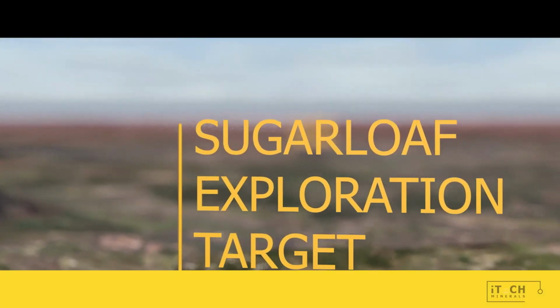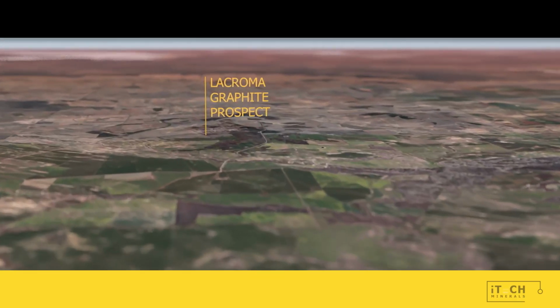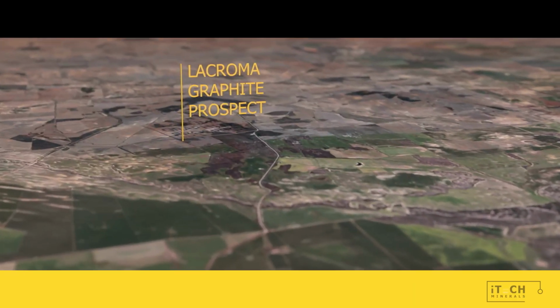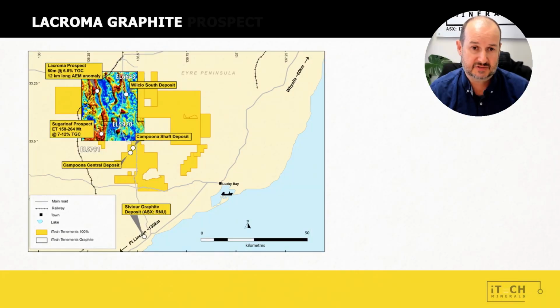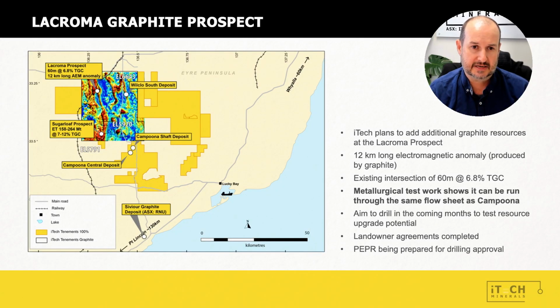So the next target we have is Lacroma. Now, this is also a very large drill target. This is part of a 12-kilometre electromagnetic anomaly, which we believe is produced by the graphite. The electromagnetics, as you can see in the multicoloured image, map out the conductivity of the ground beneath the surface. Because graphite is used in lithium-ion batteries, it is known to be a very good conductor. So it shows up as quite bright red blobs or linear features within that image.